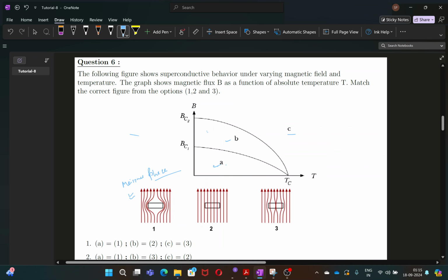So here there comes a phase called mixed phase, where the vortices appear in the superconductor. So in the mixed phase, it is not completely normal and not even completely superconductor. So the field lines will now be able to penetrate the sample, but only through some localized regions that have turned into normal, and they are called the normal regions.